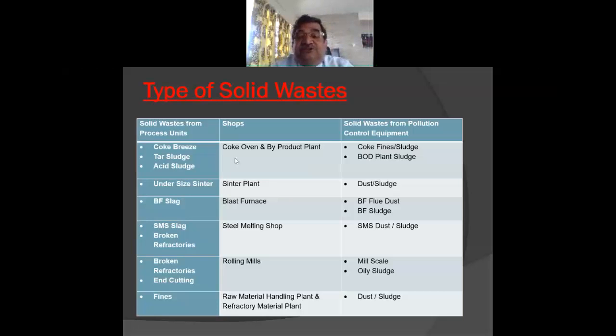Then acid sludge in the pickling lines when we do tinning or galvanizing. The surface of the sheet has to be pickled for cleaning. That is called the pickling line. It is done through acids, either hydrochloric or sulfuric acid, so it also forms a lot of acid sludge. And then gaseous waste: as you know, whenever we burn, a lot of flue gases get generated. Fumes are generated by means of cooling. Then acid fumes when we are doing pickling. The whole area is quite filled with acid fumes.